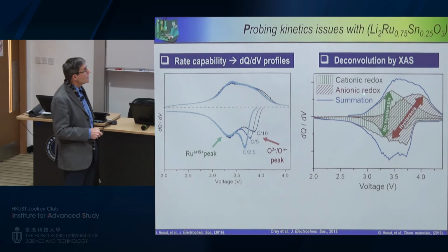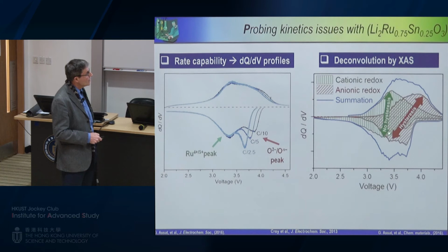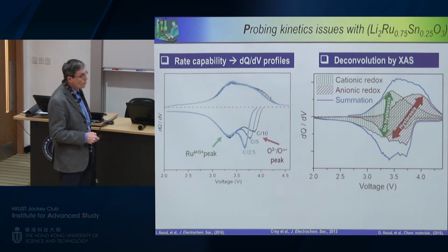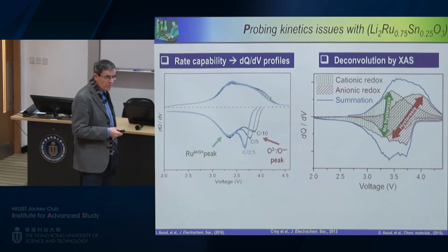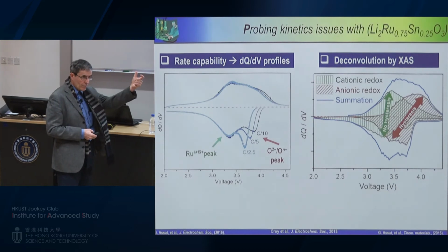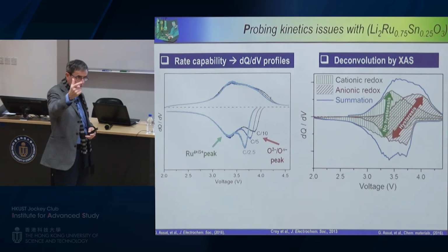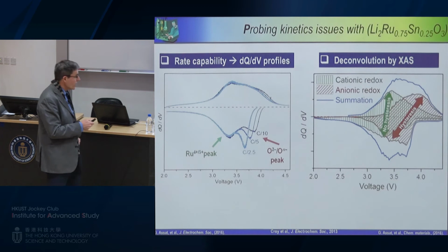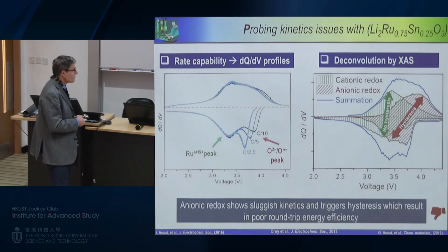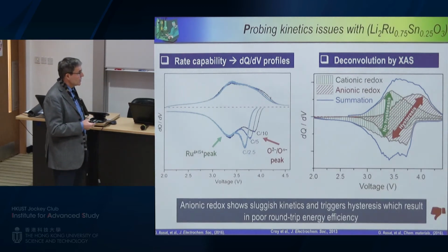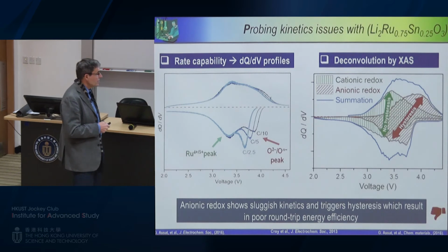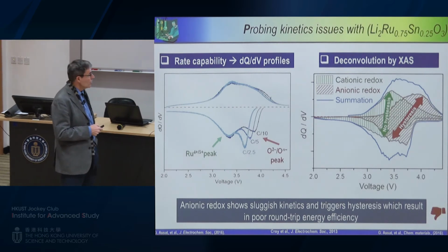And we can understand this. We have done this, you can deconvolute these two systems, and you can see that you have no hysteresis regarding the cationic redox couple, while you have hysteresis looking at the anionic redox couple. And of course, this anionic redox shows very sluggish kinetics and triggers hysteresis, which results in poor round-trip energy efficiency and heating and so on.